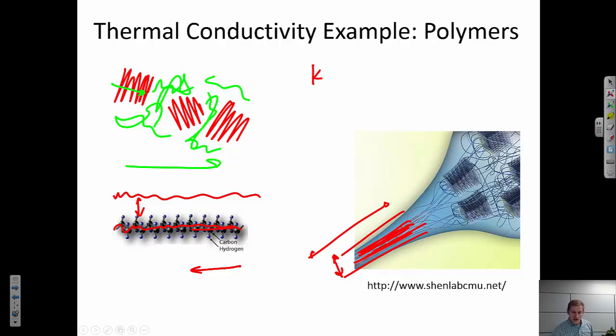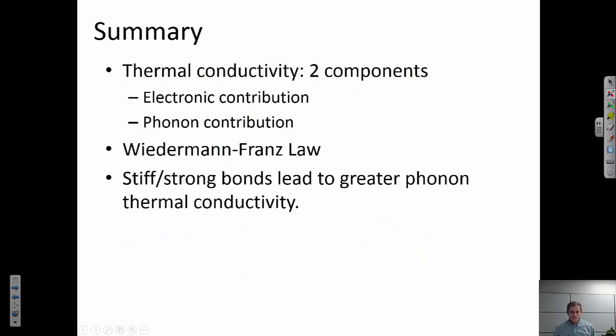And by doing that, they were able to align a lot of the polymer chains along the length of that fiber. So then, when they measured their thermal conductivity along the length of the fiber, they got thermal conductivities that were orders of magnitude higher than what we usually see in polymers. So again, the reason why is that we're thinking about thermal conductivity. We're thinking about the two contributions.